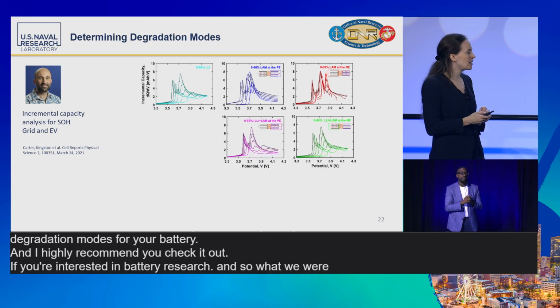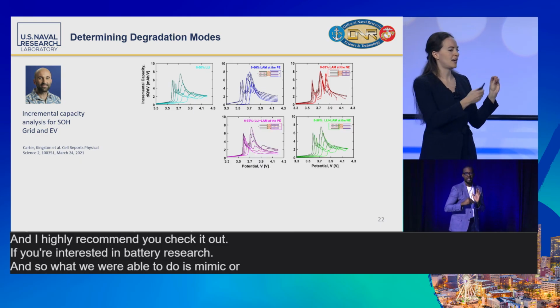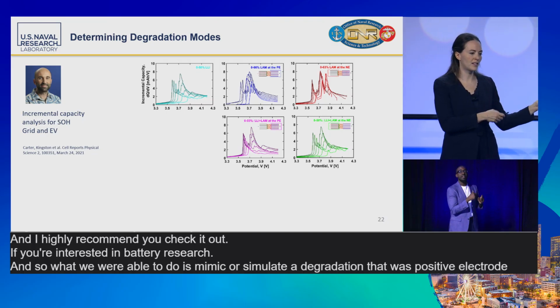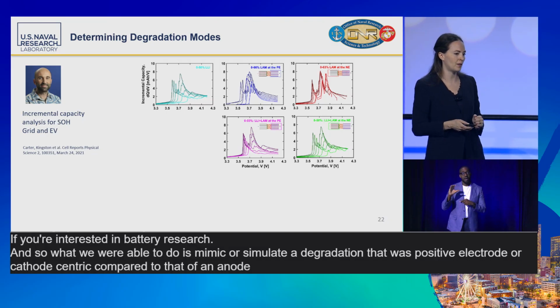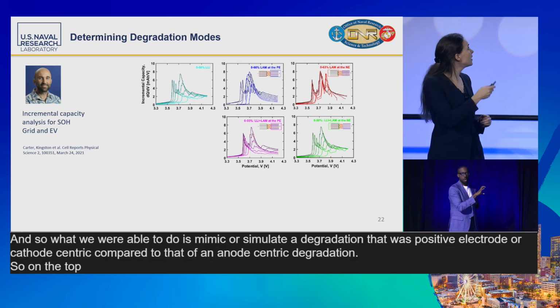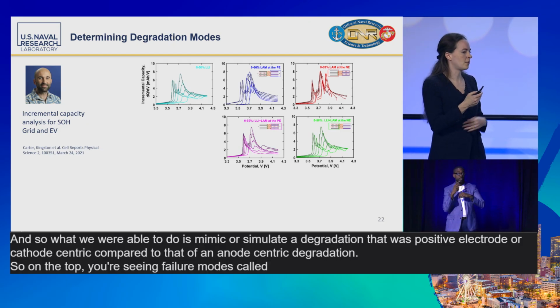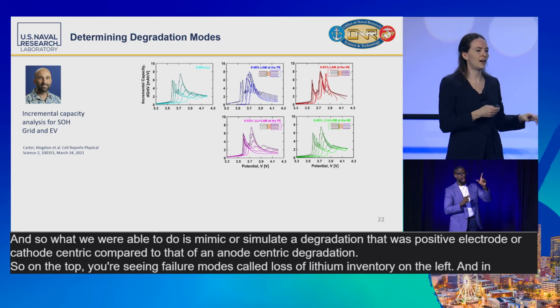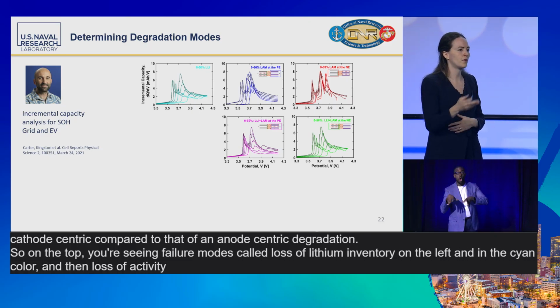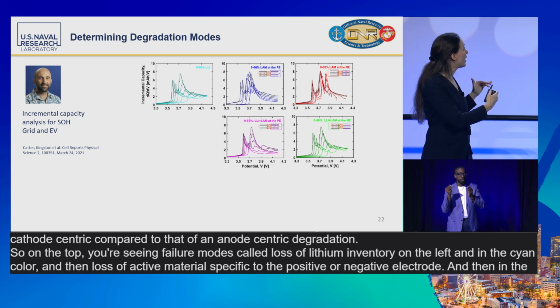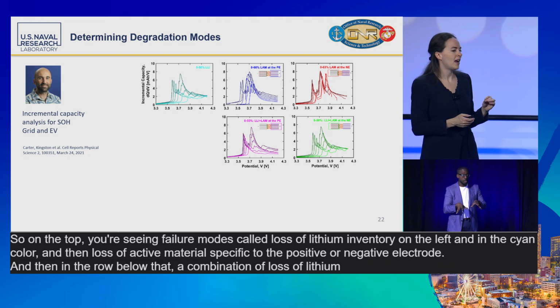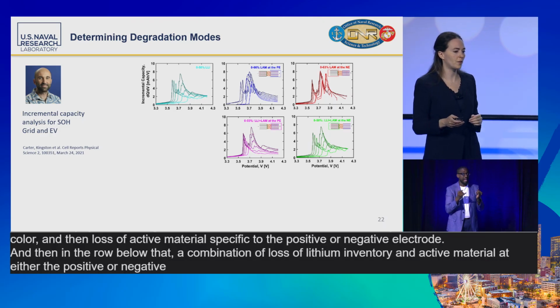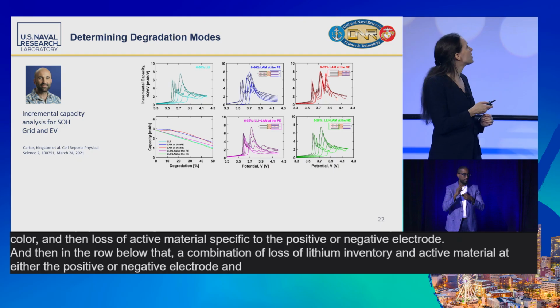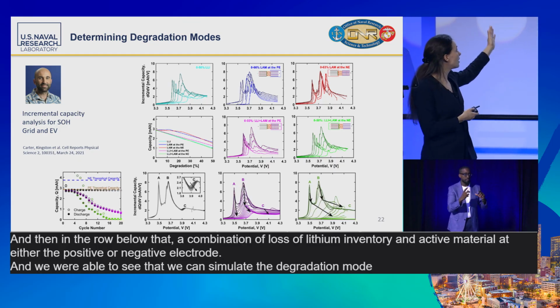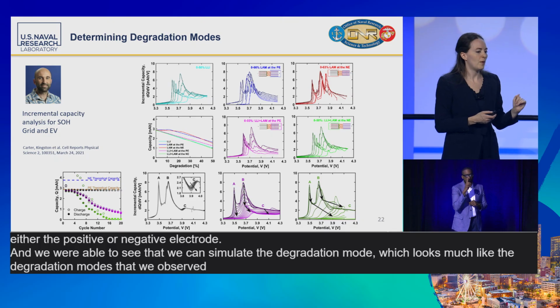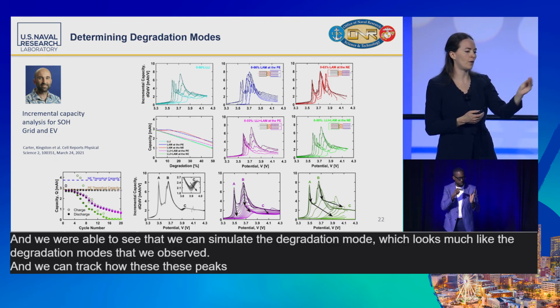What we were able to do is mimic or simulate a degradation that was positive electrode, or cathode-centric, compared to that of an anode-centric degradation. On the top, you're seeing failure modes called loss of lithium inventory on the left in the cyan color, and then loss of active material specific to the positive or negative electrode. In the row below that, a combination of loss of lithium inventory and active material at either the positive or negative electrode. We were able to simulate the degradation mode, which looks much like the degradation modes that we observed, and we can track how these peaks are evolving over the cycles.